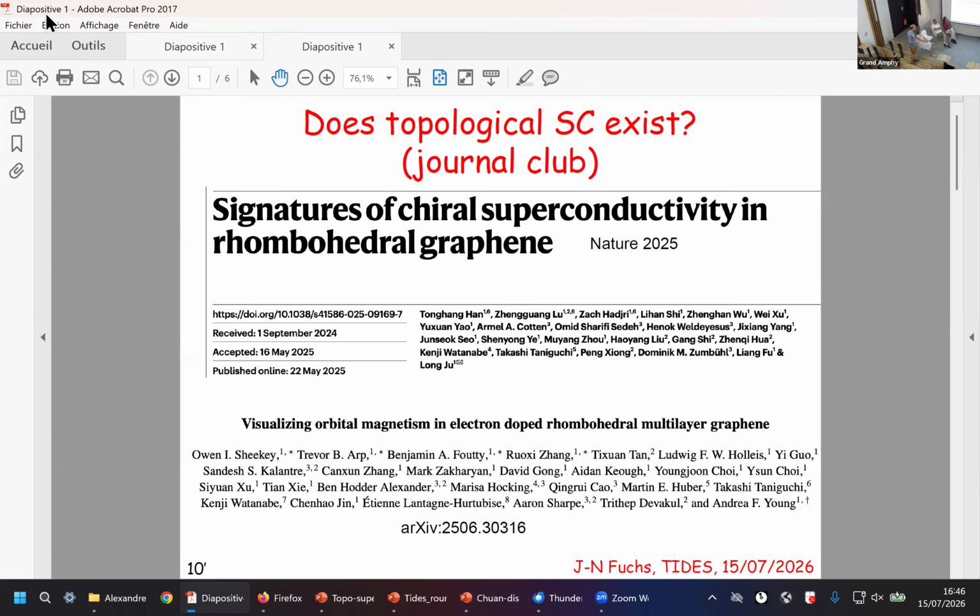It's very interesting. It's recent stuff about graphene. It's another variation around graphene. It's not monolayer. It's not bilayer. It's not twisted graphene. It's not about moirés. It's about this new kind of stacking, rhombohedral, which is ABC, etc. stacking. And the trick there is that it's crystalline, but the band structure becomes very flat when you have like 4, 5, 6 layers.